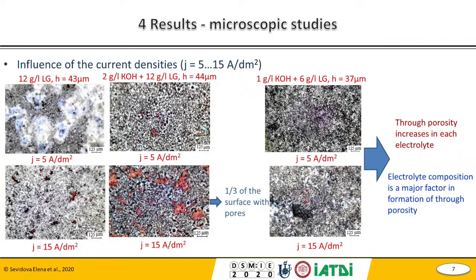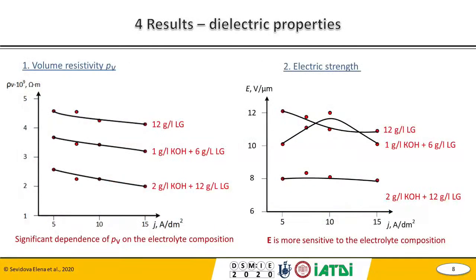And after such research, we started to research our dielectric properties. Please, slide 8. It can also be seen that there is a good correlation between these measurements, our morphology and dielectric properties. For example, the lowest volume resistivity we have is in samples with the largest amount of through porosity.